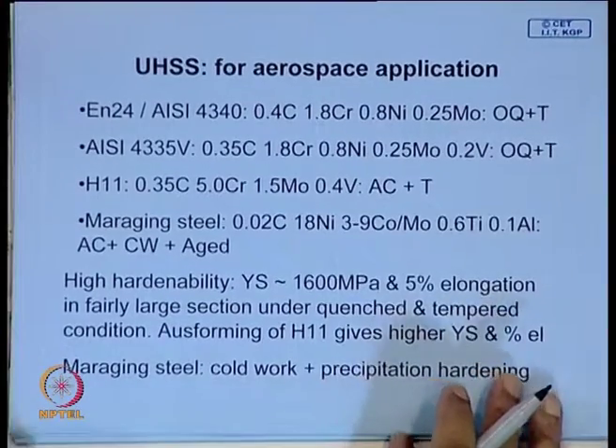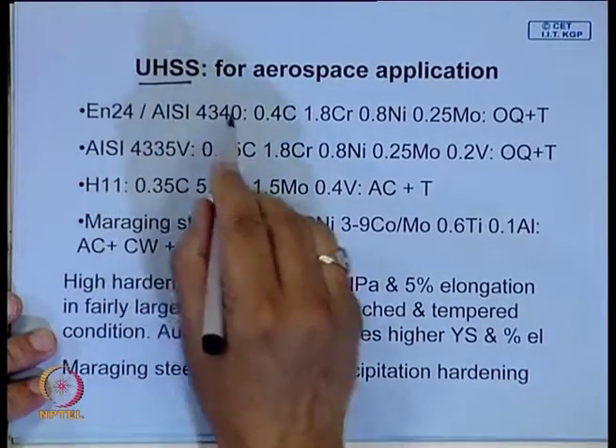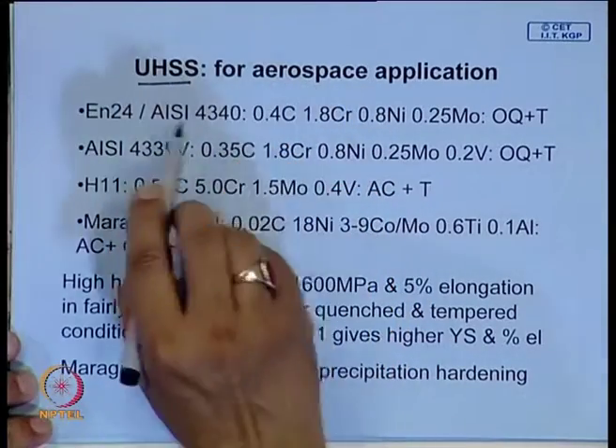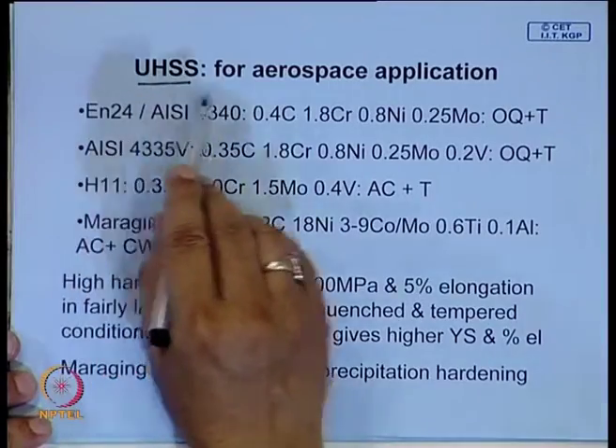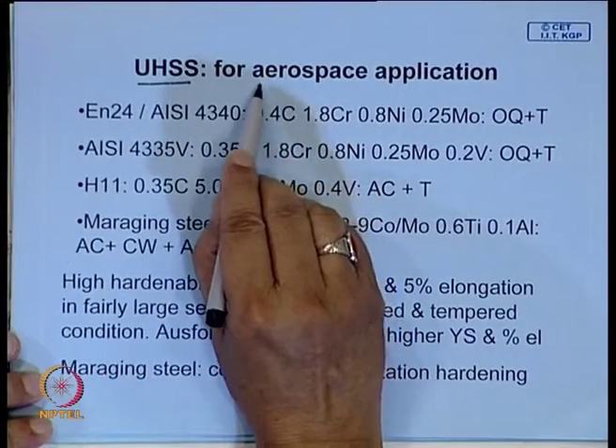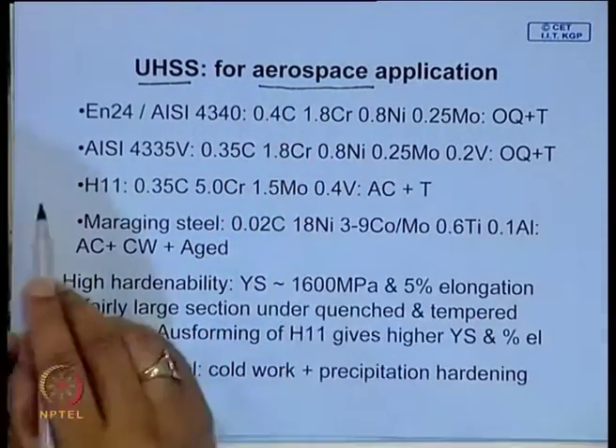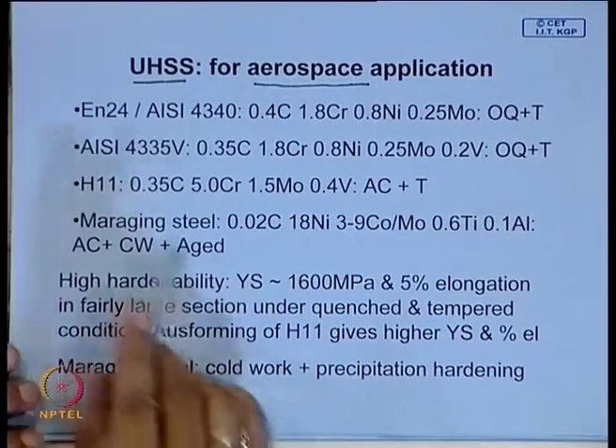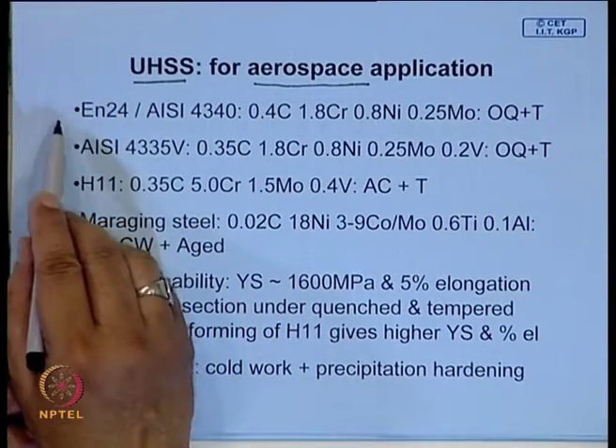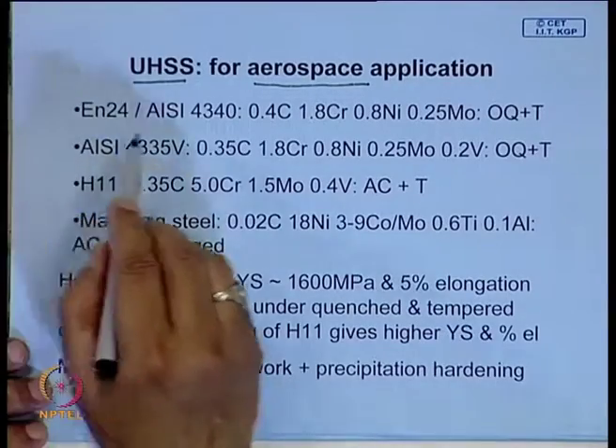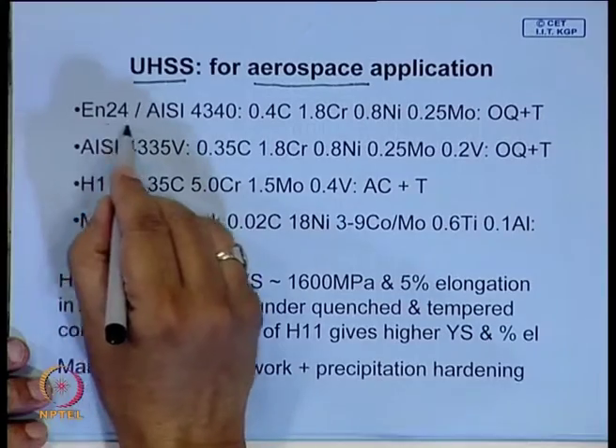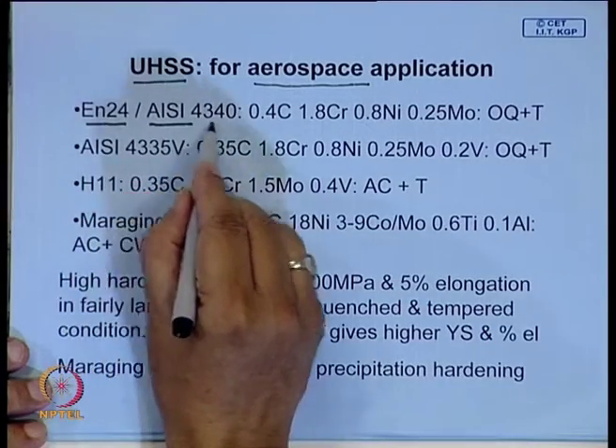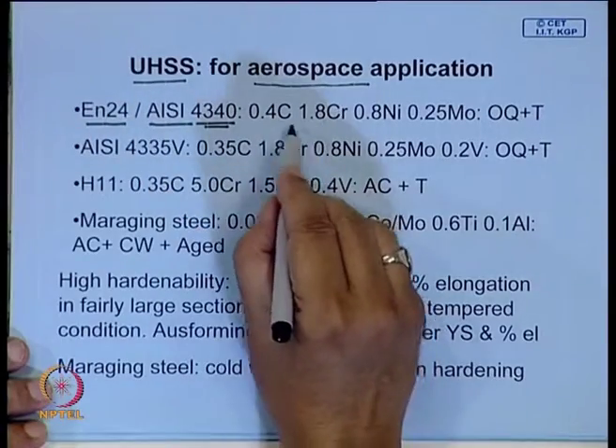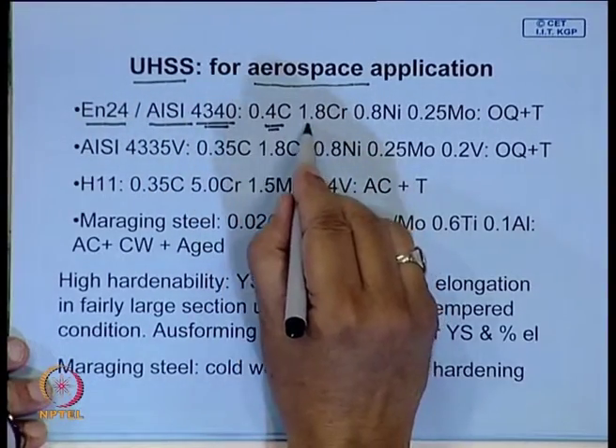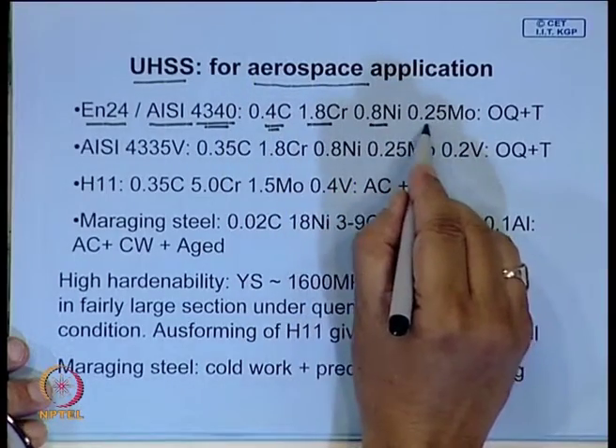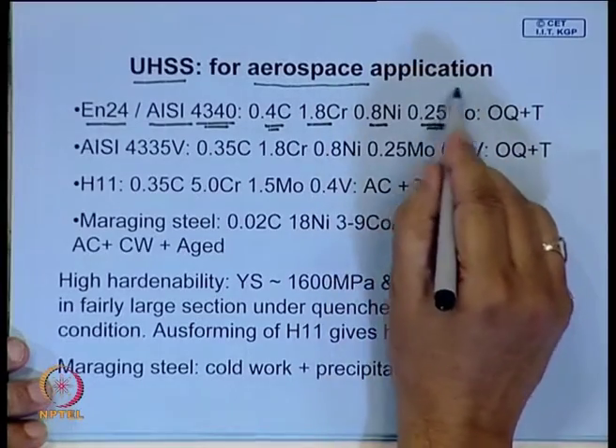Let us look at a few common ultra high strength steels. Many of these potential applications, obviously, have so much alloy element that they are expensive, but nevertheless, in applications like aerospace, cost may not be a major limitation, because one major criterion is that the structure should be light and it should be able to fly. So, this is the composition; a very popular grade is EN24 or AISI 4340, by which it is known. The composition is 0.4 carbon, 1.8 chromium, 0.8 nickel, 0.25 moly. The moly takes care of many of these issues.